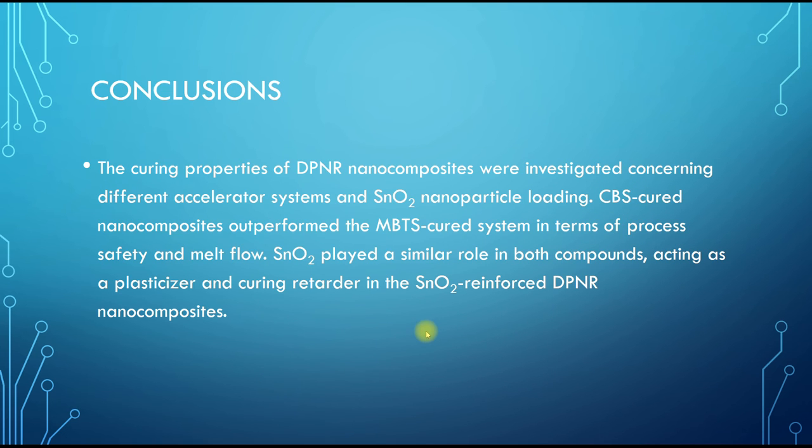The curing of DPNR was investigated concerning different accelerator systems and different tin dioxide loadings. The CBS-cured nanocomposites performed better than the MBTS-cured system in terms of process safety and melt flow. Tin dioxide played a similar role in both compounds, acting as a plasticizer and curing retarder in the reinforced DPNR nanocomposites.